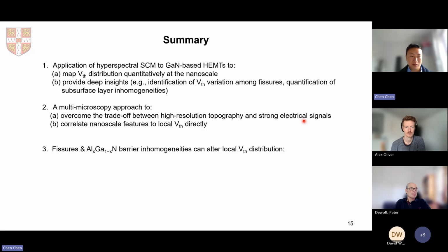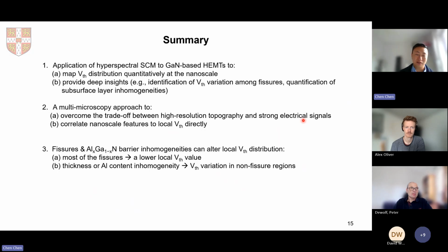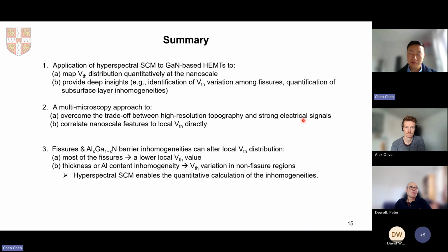For our sample, we found that both fissures and aluminum-bearing inhomogeneity can alter the local threshold voltage distribution. In detail, we found that most fissures reduce the local threshold voltage value, and thickness or aluminum content inhomogeneity can cause threshold voltage variation in non-fissure regions. Hyperspectral SCM enables quantitative calculations of these inhomogeneities.